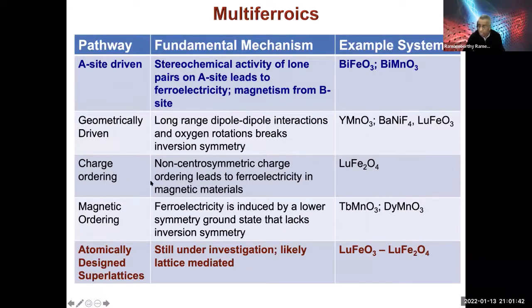You could have charge ordering, like a Verwey transition. These are not very robust materials. There's been a lot of debate in the community whether these are really multiferroic, how robust is the ferroelectric state there. This is the one where the ferroelectric and the magnetic state are very robust at room temperature. So not a big surprise that a lot of people are looking at bismuth iron oxide or chromium oxide. I mean, Wolfgang has done some spectacular work in that direction, and Christian Binek at Nebraska has done some beautiful work on that system as well.